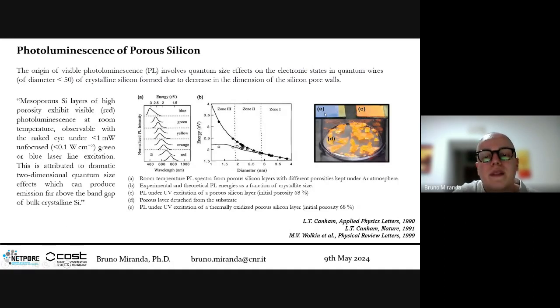But what happens if you oxidize this porous silicon? It directly becomes blue. So the photoluminescence is something that is very unstable. So we need several strategies to passivate these structures and try to improve their chemical stability and also their photoluminescence.